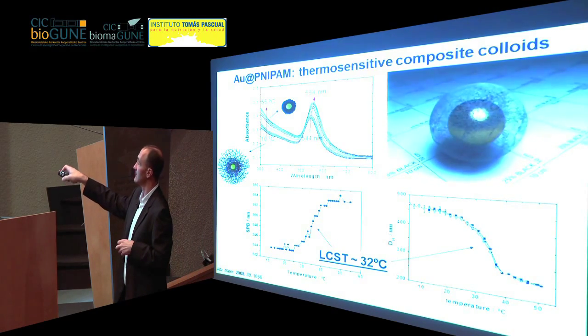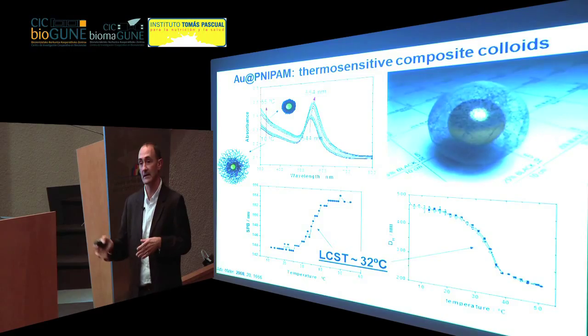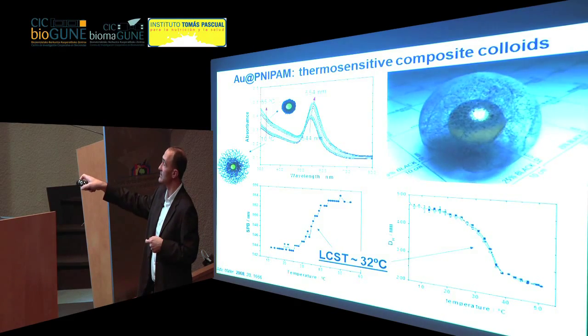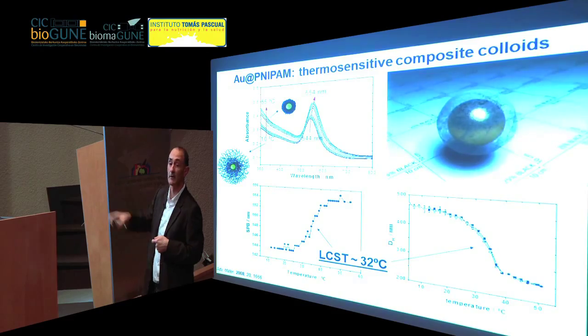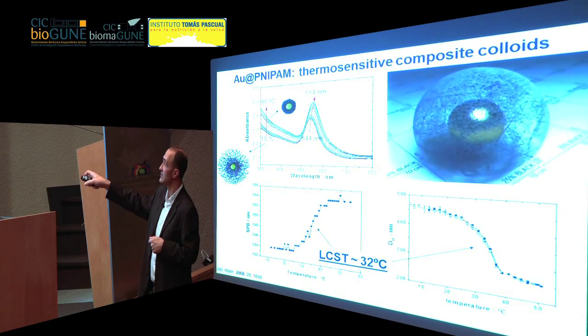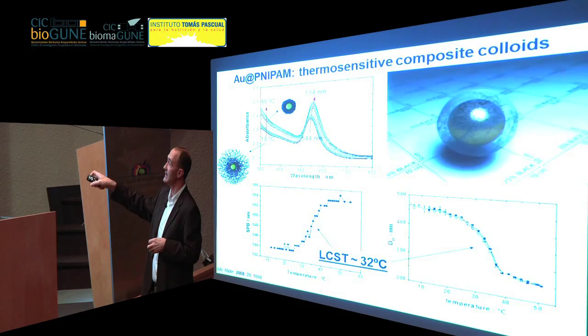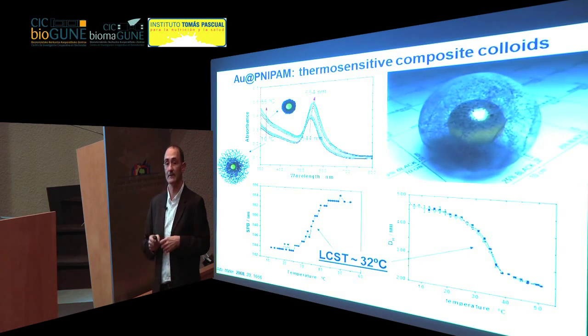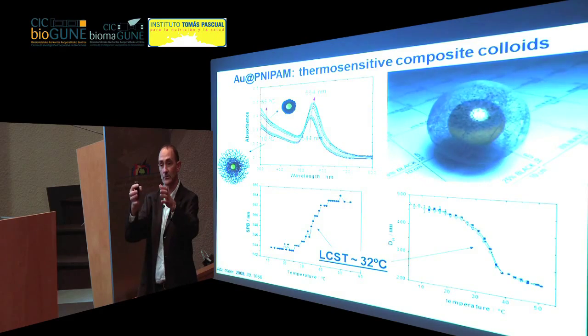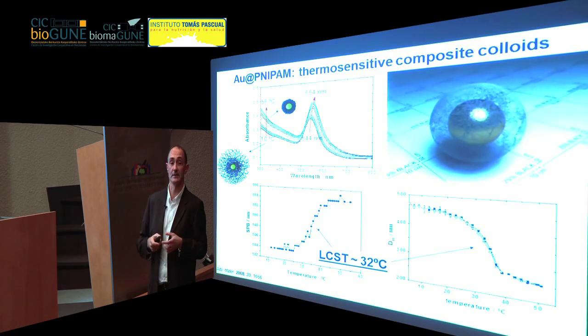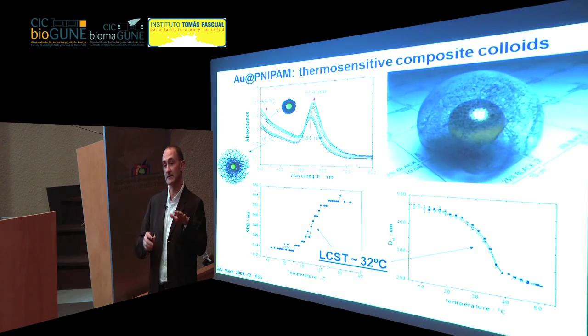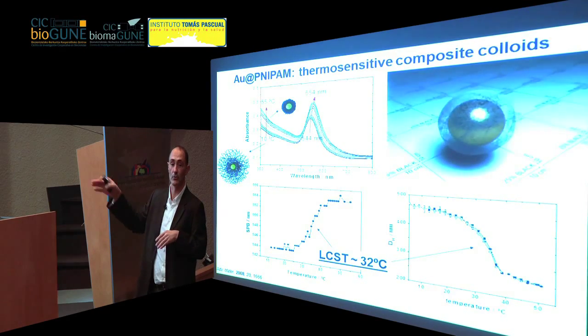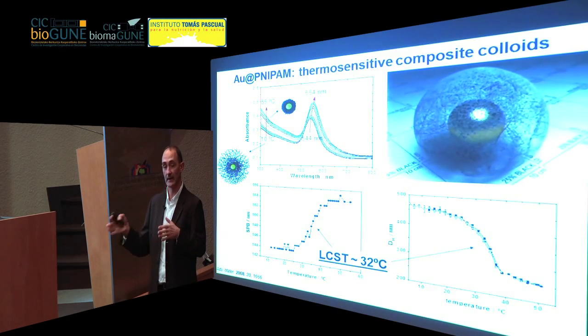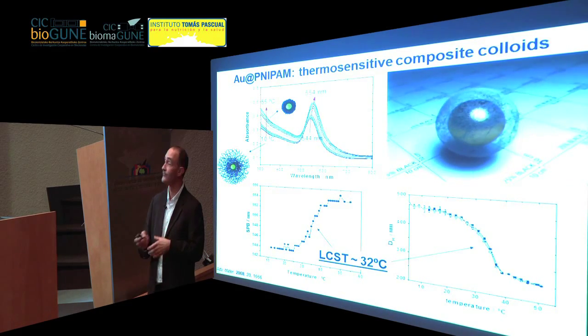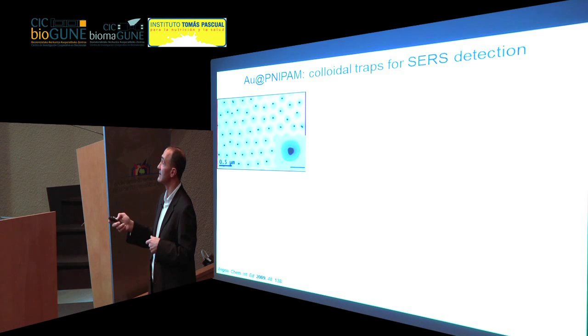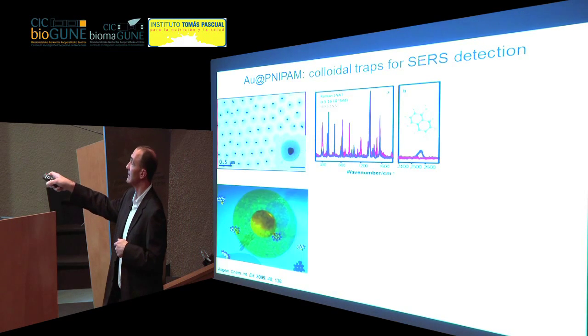So we measure the changes in the size and we see the same thing as for the polymer alone. We can also check the changes in the maximum of the plasmon resonance, and we also see changes which are fully reversible, and this is because we are also changing the refractive index around the particle when the polymer collapses on top. This is very similar to the surface plasmon resonance biosensor. In that case, you're watching changes in the reflection conditions. Here, you're watching changes in the absorption conditions, but it's all related to changing the refractive index close to the surface.